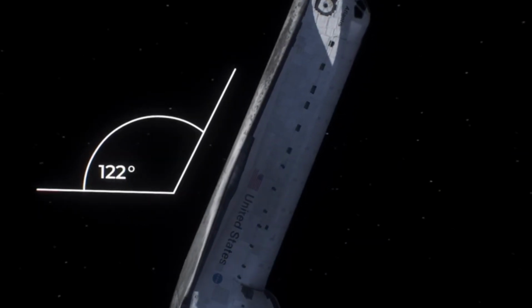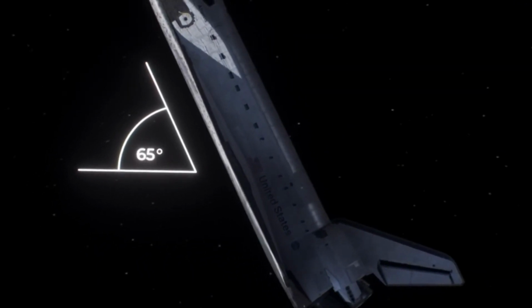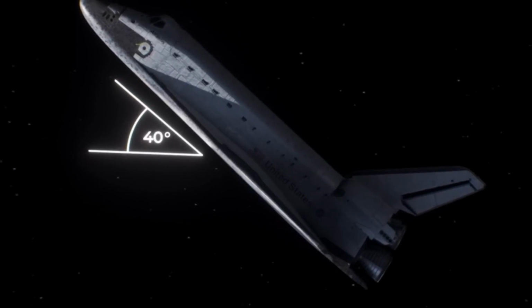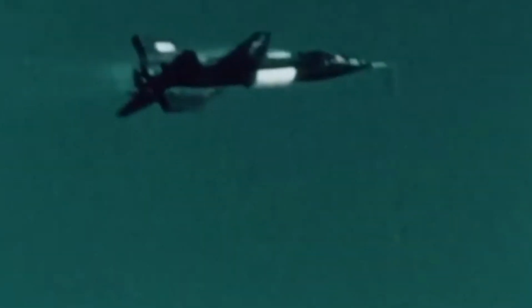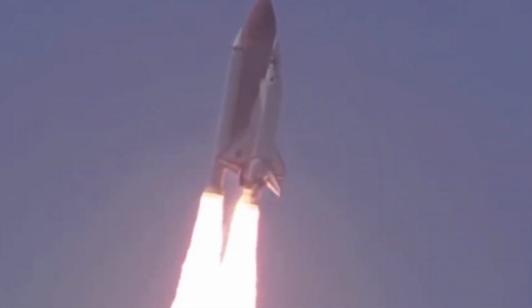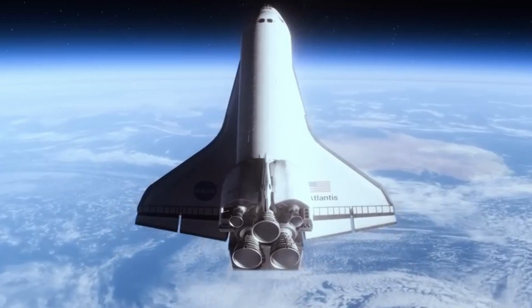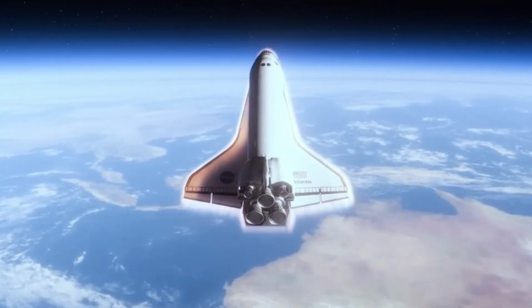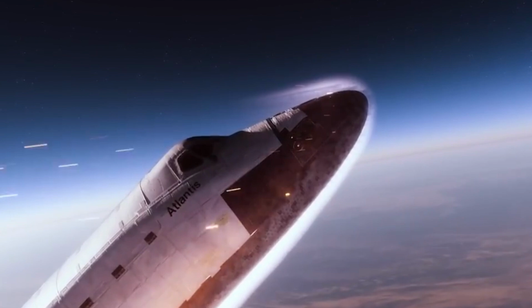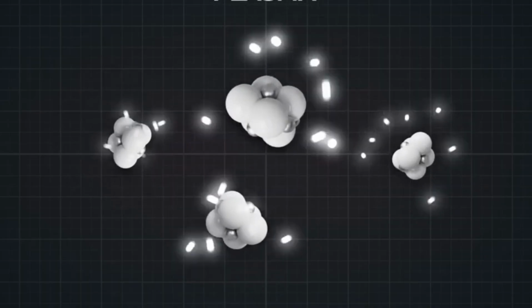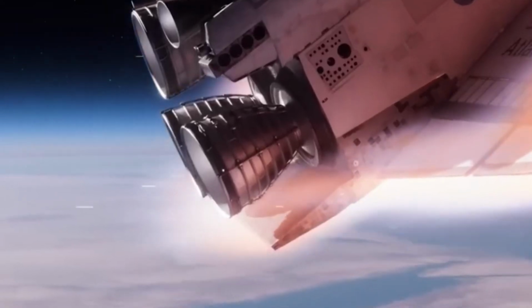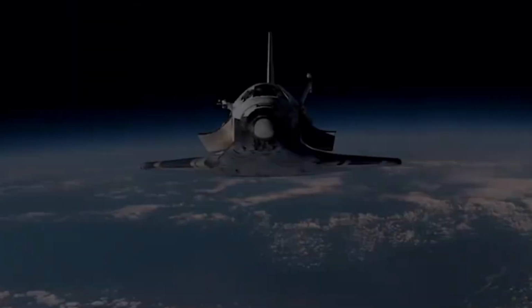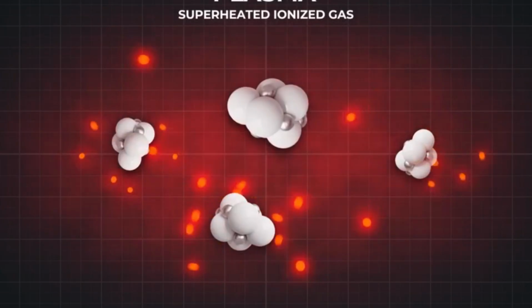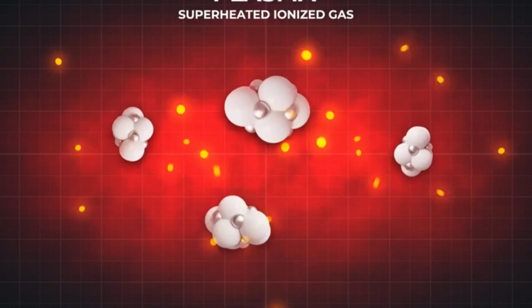This allowed the X-15 to use a state-of-the-art advanced heat-resistant aerospace metal, Inconel X, with a maximum operating temperature of 980 degrees Celsius, 1800 F. The Space Shuttle could not use this metal because Inconel X is too heavy, about 180% heavier than an equivalent aluminum airframe, a massive issue for an aircraft designed to be carried into orbit. The Space Shuttle's airframe, therefore, is not made from Inconel X but is composed of lightweight aluminum, which has a maximum operating temperature of just 177 degrees Celsius, 5 times lower than Inconel X. The orbiter would experience temperatures 10 times greater than this for extended periods of its re-entry flight.